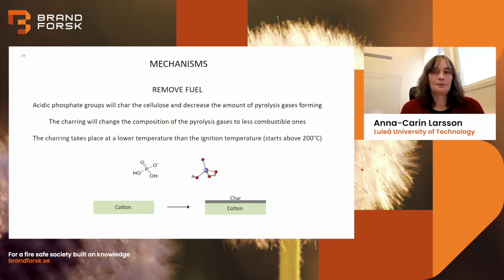And then in the next step, we will remove the fuel. So those acidic phosphate groups that have formed, it will be like phosphoric acid, they will char the cellulose. And that will decrease the amount of pyrolysis gases forming, because instead of decomposing the cotton into pyrolysis gases, we form this char. But there will still be some pyrolysis gases forming, but since this charring starts at the low temperature, the composition of the pyrolysis gases will be different than if this decomposition takes place at 370 degrees. So this composition will also minimize the risk of fire because they will be less ignitable.